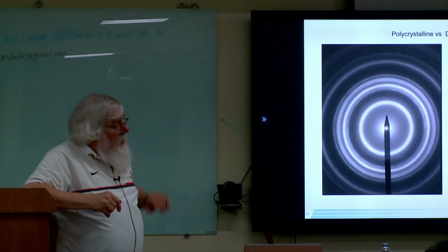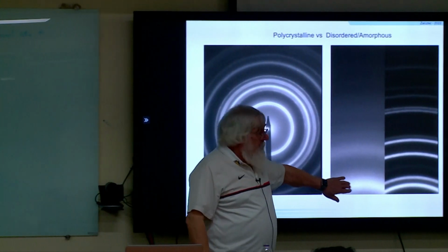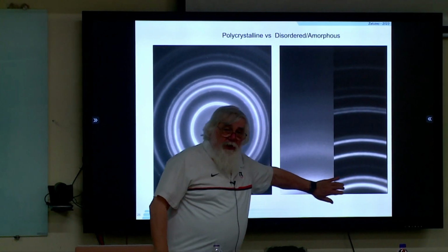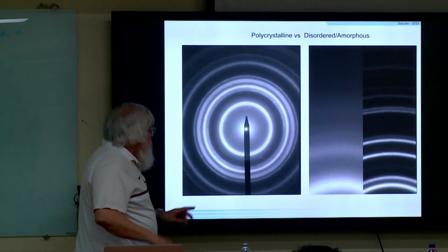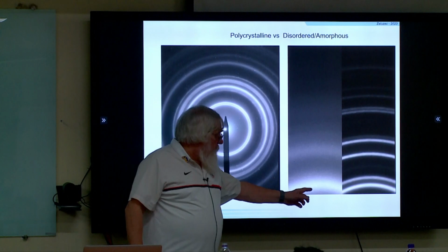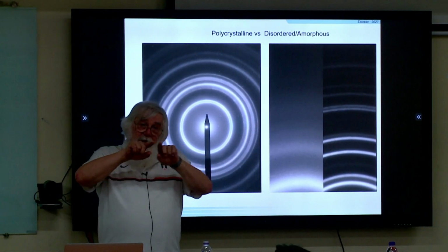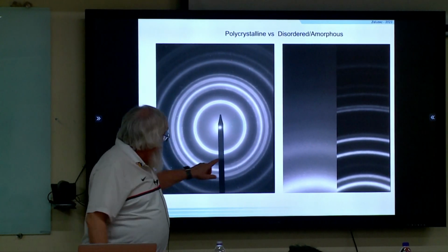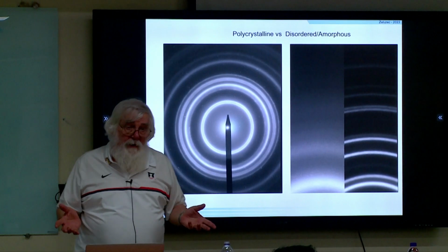These are the broad diffuse rings that we had. These are the very sharp ones. When they're very sharp, it's usually a polycrystalline material. The important thing to notice, remember, just as I told you that the periodicity of the diffuse rings was related to the spacing of the atoms, the periodicity of these rings is related to the crystal structure of the solid.